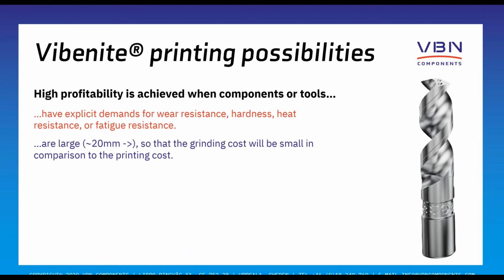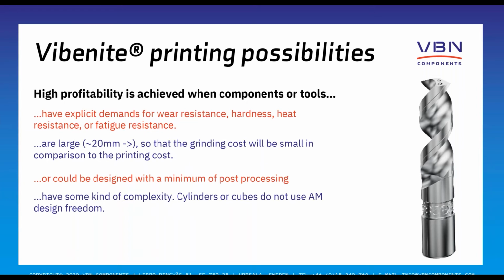And this is just a rule of thumb recommendation. 20 millimeters is not an exact value. It's just by the rule of thumb. It depends on your grinding cost, so that you can compare to the printing. You can also design components without the need for post-processing, so that you leave some surface with a rough surface that you can use. And you also need some kind of complexity.